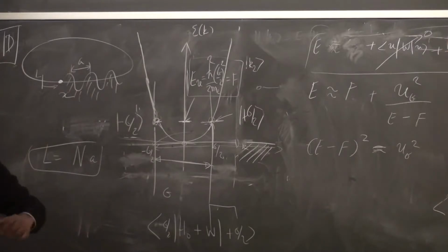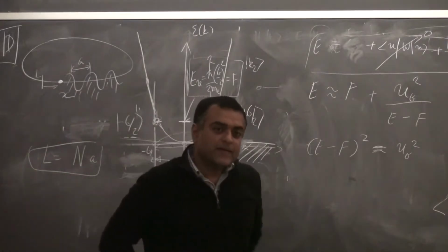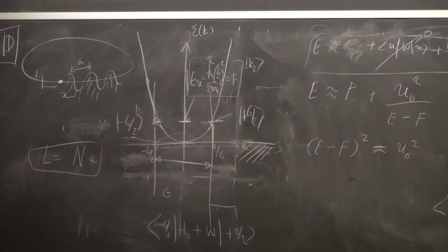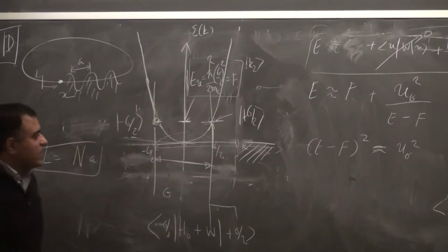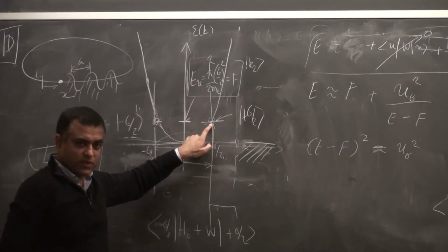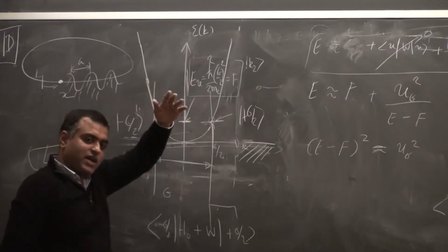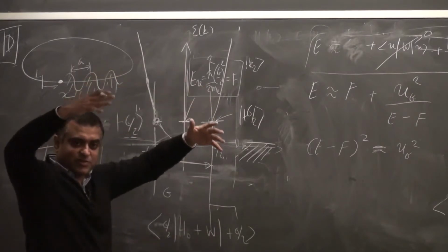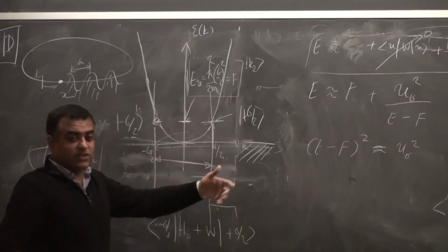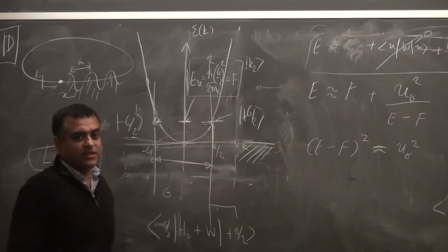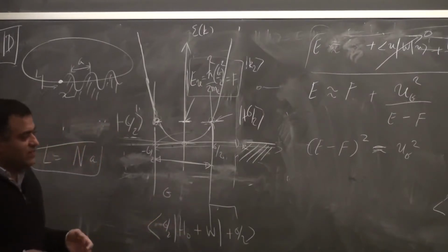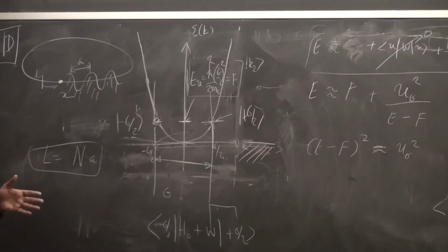So, yeah. Could I be thinking about this wrong, but at that condition, do you have a standing wave? Yes, exactly. So that's when the wavelength of that electron becomes exactly resonant with the wavelength of the perturbation. So these are two standing waves, and the upper state is when they are piled up at the highest point of the perturbation, and the lower energy state is when they're piled up at the lowest energy of the perturbation. But both electrons have formed standing waves now because of the interference and the diffraction, because the wavelengths have become resonant for the electron and the crystal.